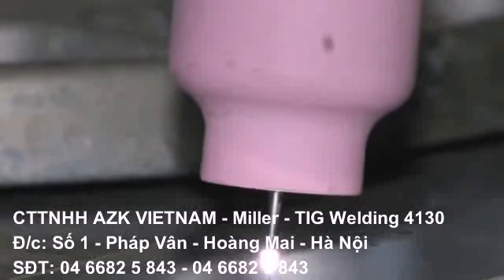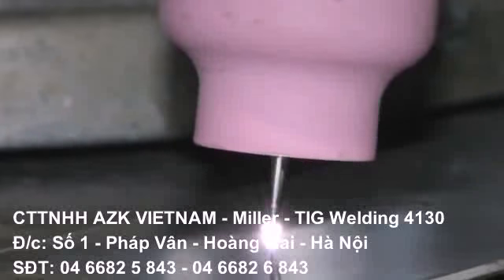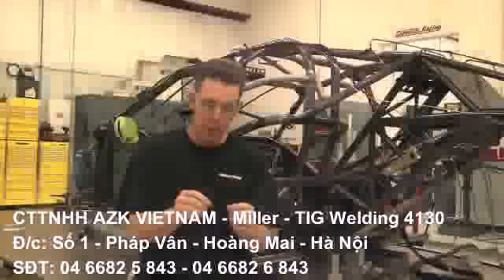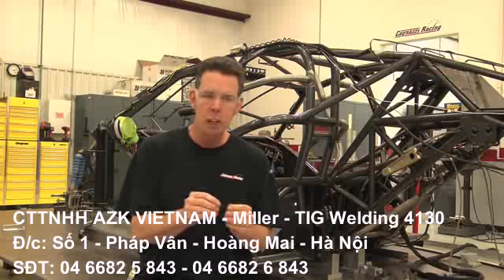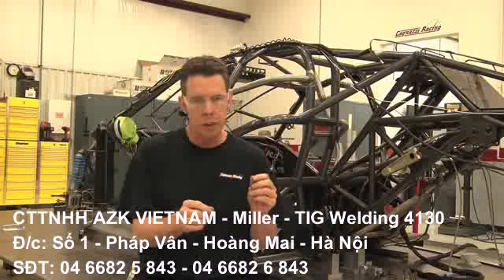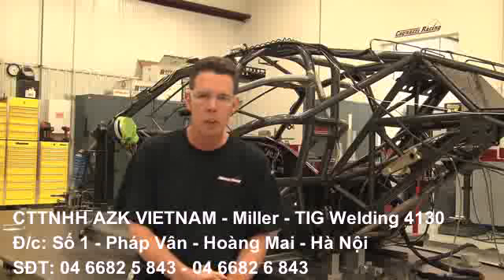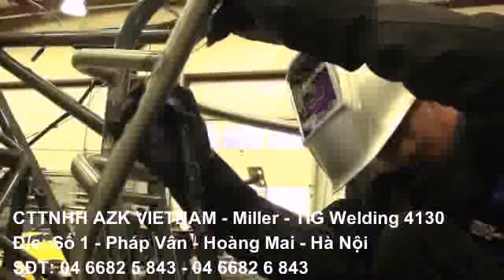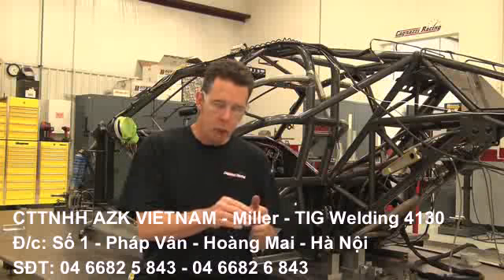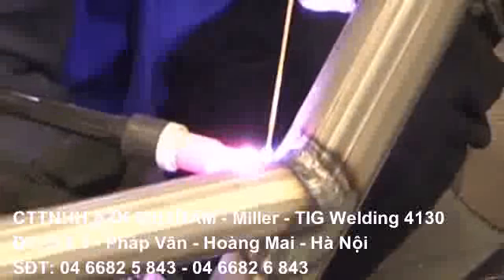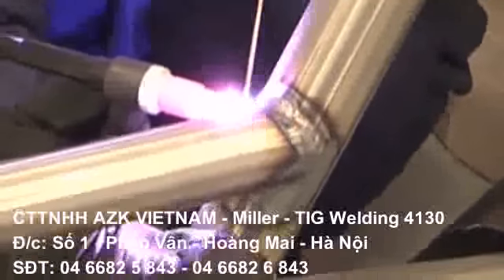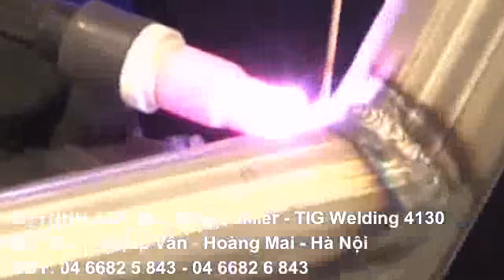Arc length is the distance from the tungsten to the piece that we're welding. And with chrome moly in TIG welding, we want to keep that arc length as small as possible without contaminating with the welding rod or touching the puddle that we're trying to weld. As the arc length gets further away, it requires more power from the welder to push that arc off of the tungsten onto the weld. So therefore, you get a bigger spark, and it's spread out wider, and there again, it's going to spread the heat. And welding chrome moly, we want to concentrate the heat in a small area.